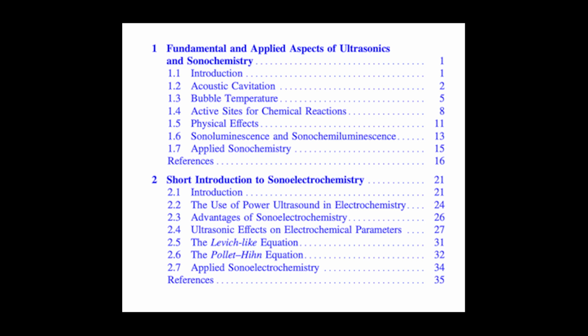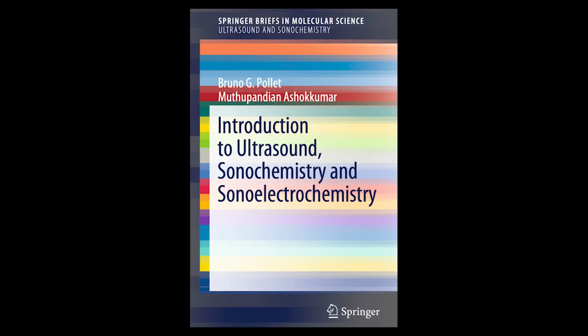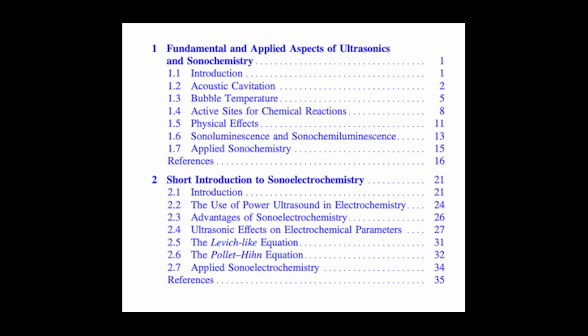Yeah, other researchers looked carefully and found no significant effect of ultrasound on k naught for the systems they studied. The electron transfer rate itself didn't seem to change. Okay, so maybe the heating effect isn't always dominant or measurable. Possibly. And then to make it even more confusing, some studies have actually reported a slight slowdown in the electron transfer kinetics for certain types of reactions, usually quasi-reversible ones, under ultrasound. A slowdown? How could ultrasound make the reaction slower?